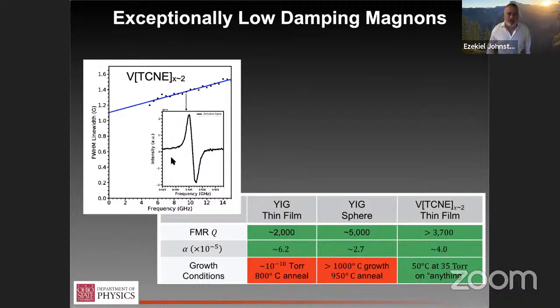So here on the inset is a single FMR resonance line scan where the frequency is just a few gigahertz. If you track that line width as a function of varying the magnetic field and hence the magnetic resonance frequency, this slope allows you to disentangle the inhomogeneous broadening, which is this intercept, from the homogeneous broadening, which is this Gilbert damping parameter alpha. And I mentioned before that YIG has been the gold standard for 50 to 75 years for microwave electronics. And this, again, I've sort of generalized to the Q factor that one can find in YIG. You can see this is a really good quartz crystal or a pretty bad optical cavity is the phase space that's available. The Q factor of VTCNE beats YIG thin films and is comparable to YIG spheres. And this number is improving sort of all the time.